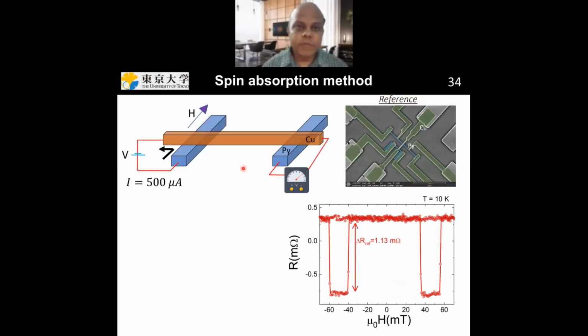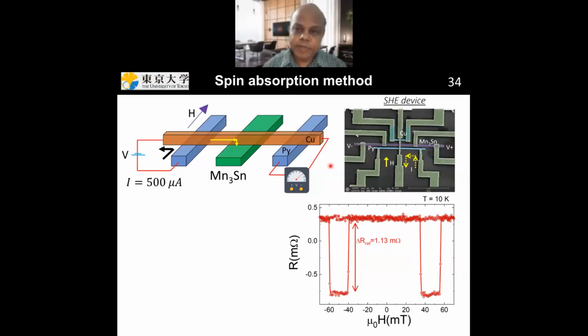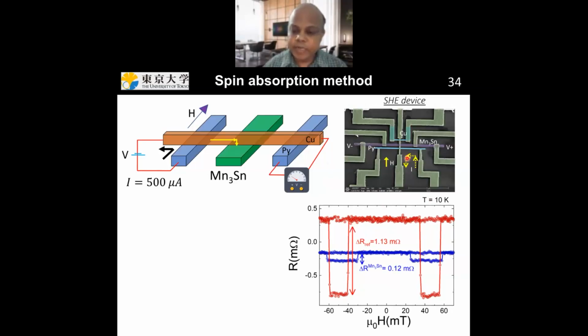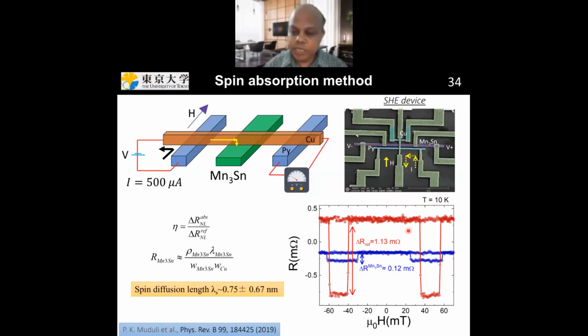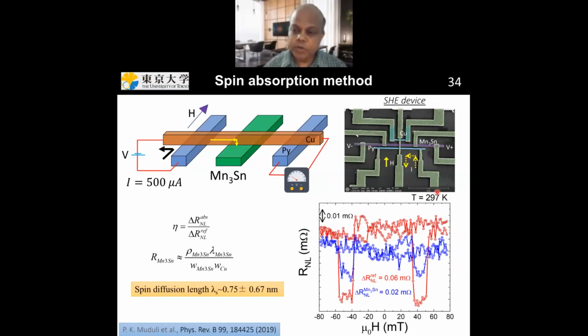After that, we follow the same spin absorption method. We make one simple non-local spin valve device and measure the spin signal, which looks something like this. Now if you put the Mn3Sn in the middle and measure the spin signal, you can see the spin signal is reduced, and this measurement is done at 10 Kelvin. If you do the same measurement at room temperature, you can still see the spin signal is reduced. From this reduction of the spin signal, you can calculate the spin resistance, and from this the spin diffusion length of Mn3Sn, which I found to be very small, around 0.75 nanometers.